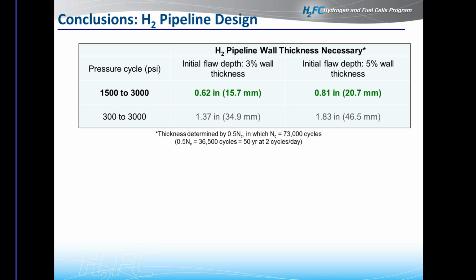The other critical variable is the initial flaw depth. So we assumed that with modern technology, we could probably measure wall thickness flaws on the order of 3% of the wall thickness or 5% of the wall thickness in this column. And so from that, we can perform these fatigue life calculations now that we've measured the fatigue crack growth relationships of these pipeline base metals.